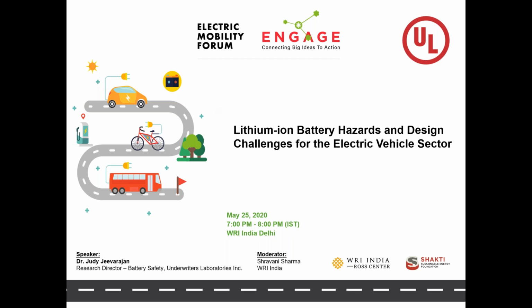And this is something we actually see in our environments too, in the US, where we have very cold winters and very hot summers. In the cold winters, you have to warm up the battery to a certain temperature before you can actually charge or discharge the battery. That is really important, that you do not try to charge a battery when it's very cold, because as I mentioned before, the internal resistance of the cell increases because the viscosity of the electrolyte increases, unless that electrolyte is actually made to work at really low temperatures, like less than 0 degrees C.